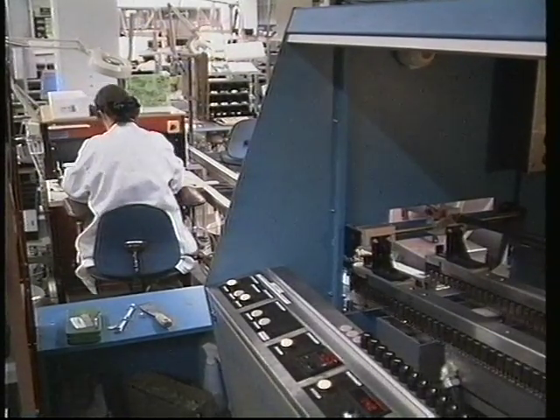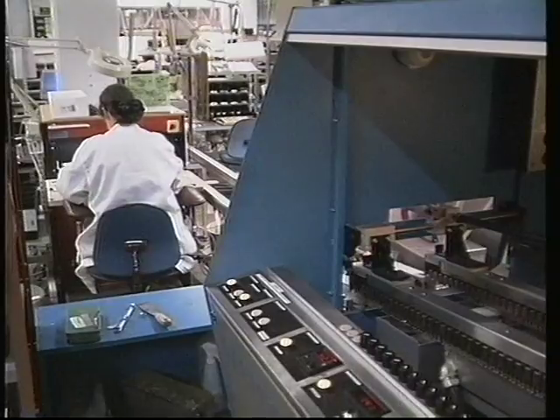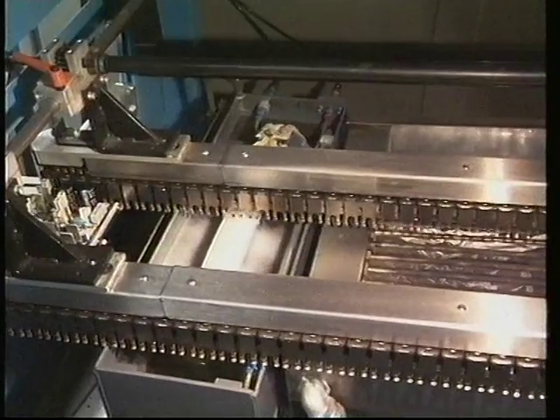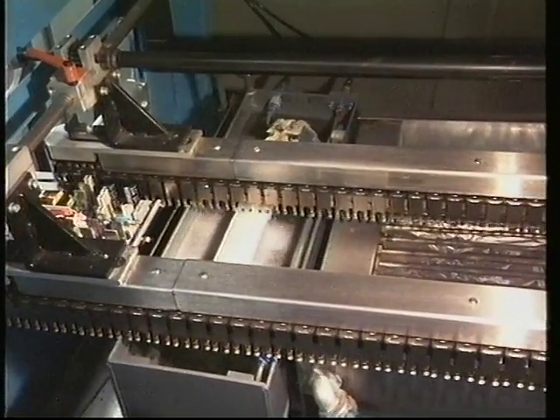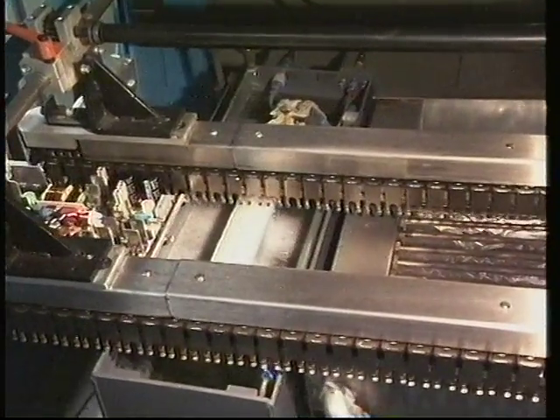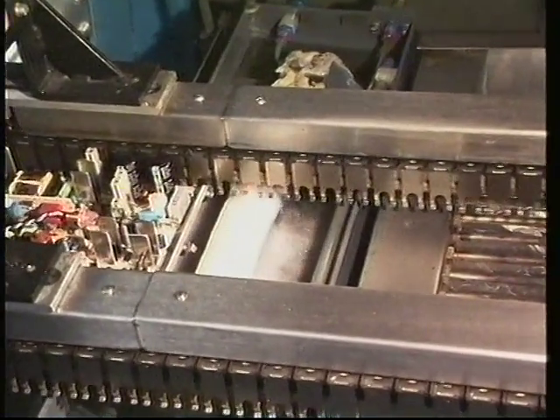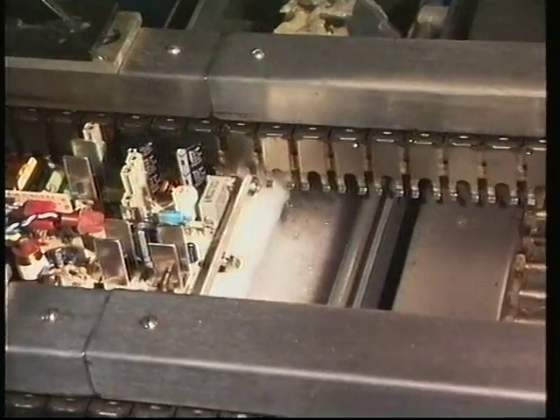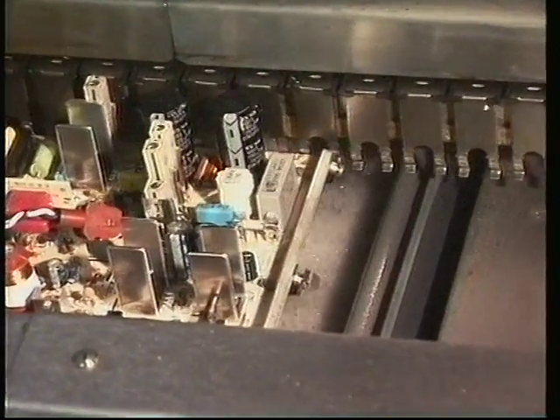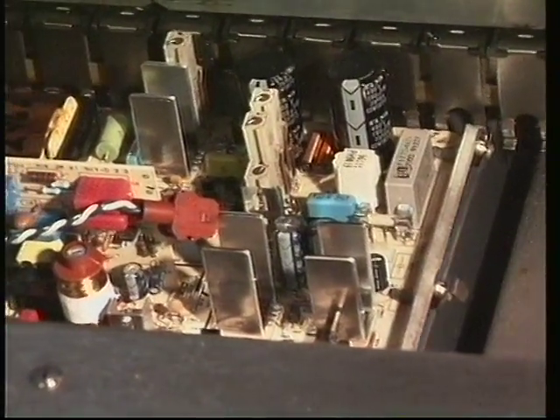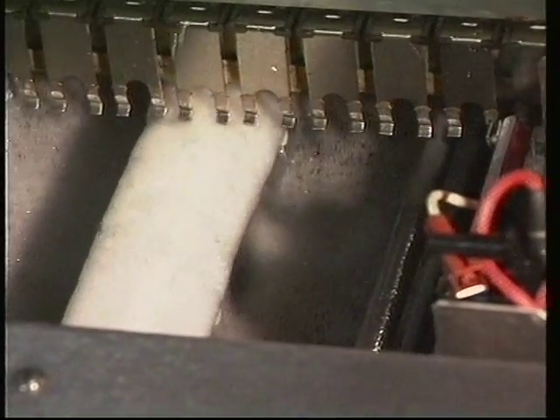Now, after automatic insertion and manual placement of odd components, the board is ready for wave soldering. The foam fluxer sprays flux mixed with air onto the lower surface before the board passes the 120 degrees centigrade heated zone. At this preheat temperature, the flux is activated and volatile solvents evaporate.